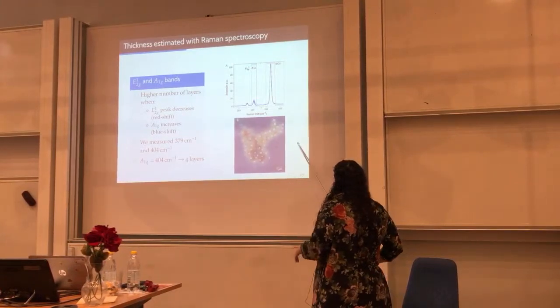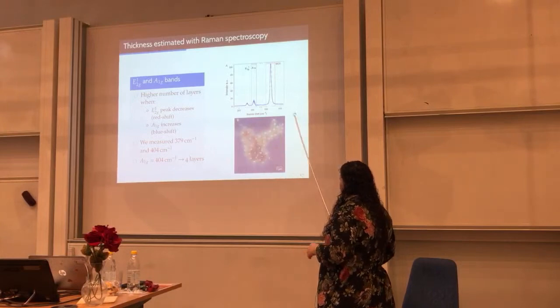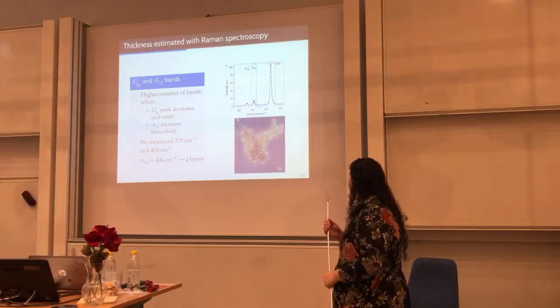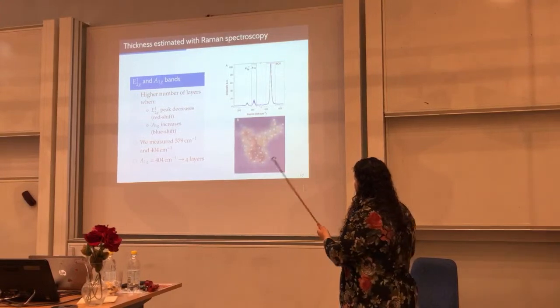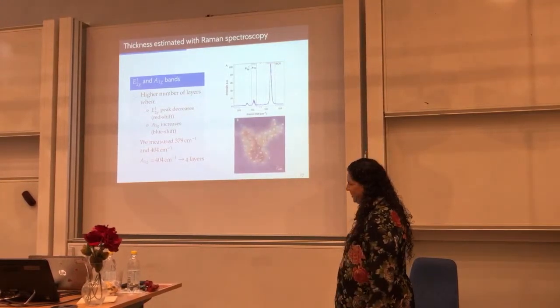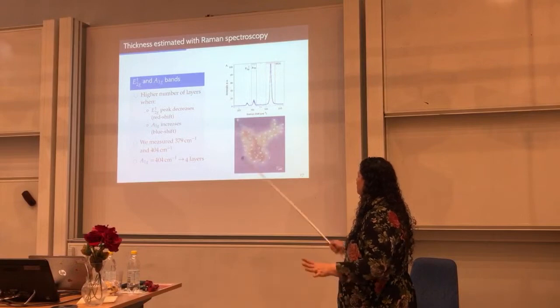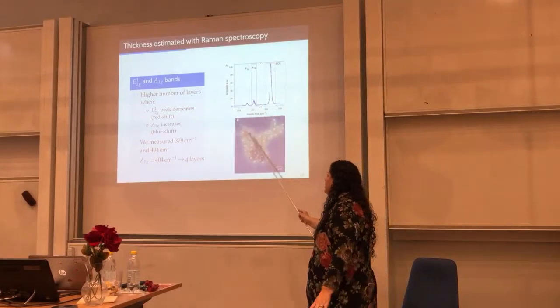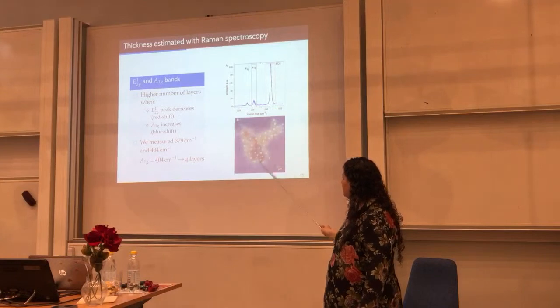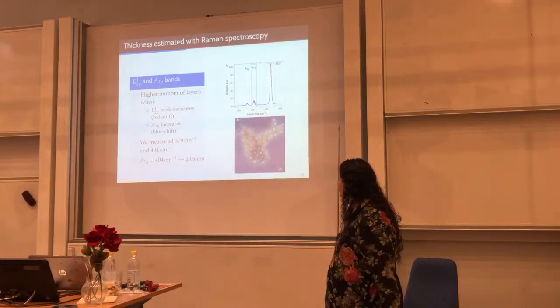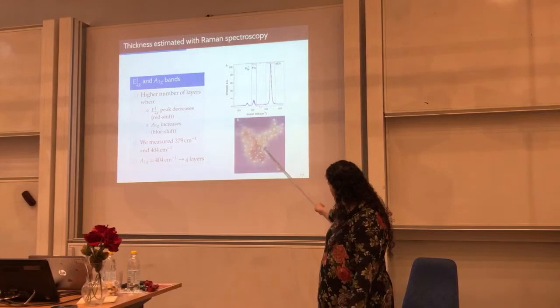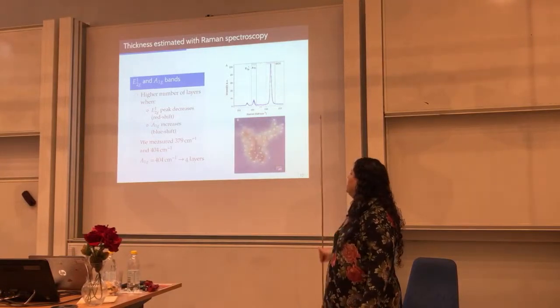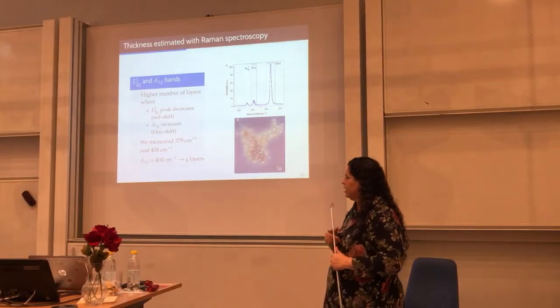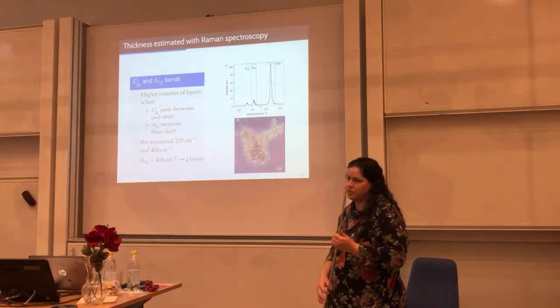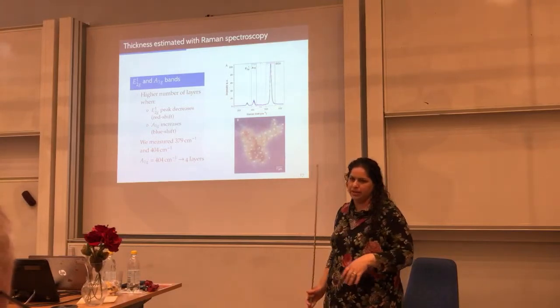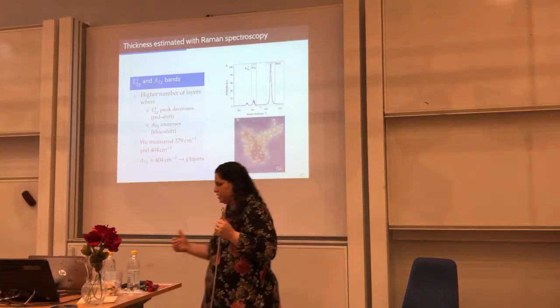This is a particle that we look at from the Raman microscope, so it's an optical image. And I did the Raman on these 39 points. And they were all in the same position, which means that I didn't have a change in thickness on this flake here, or if it's multiple flakes. But then there was this black color here, and this experiment that I talk about later on, about the adhesion, helps me to explain that actually this is probably HEC. It's probably the polymer that's attached to the surface there.